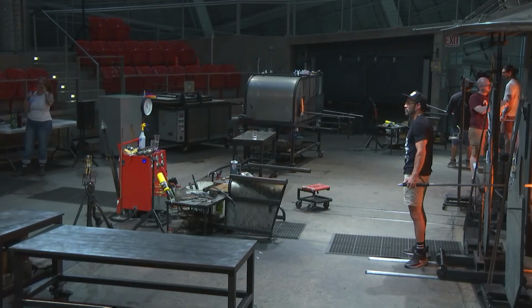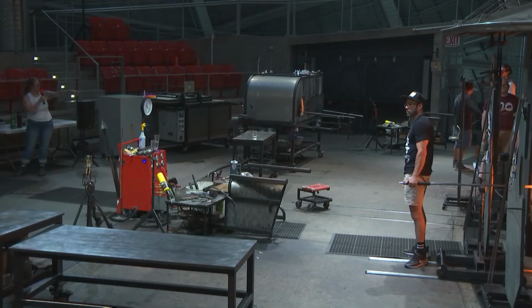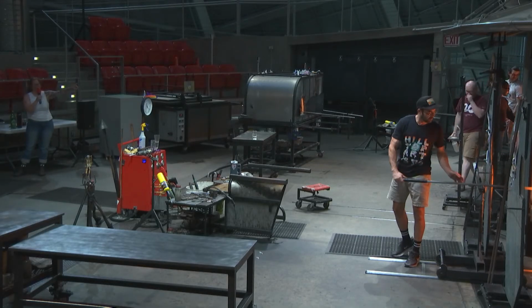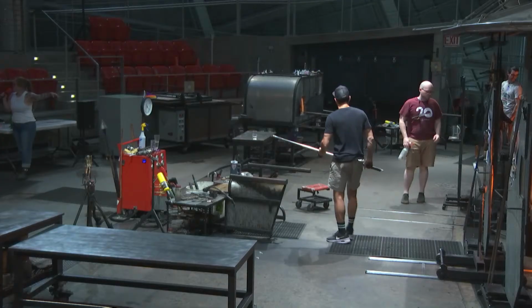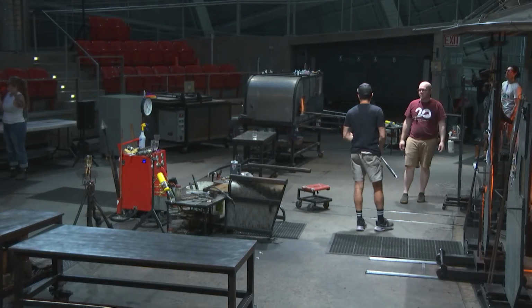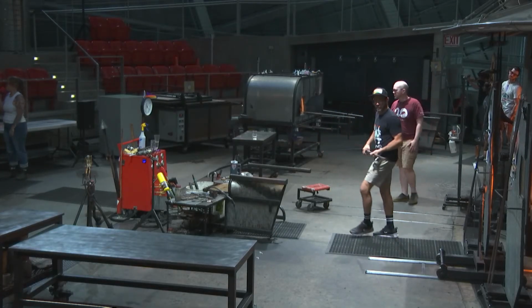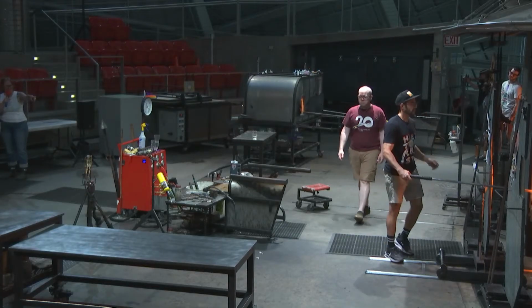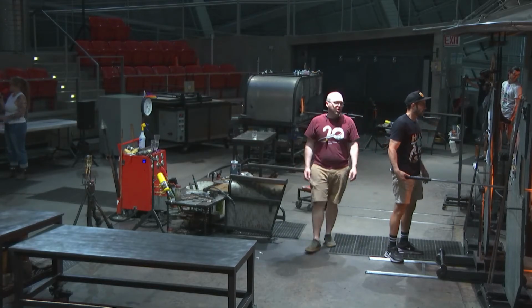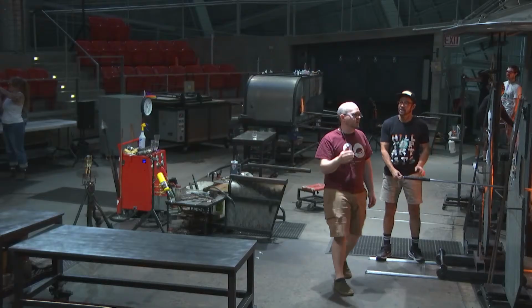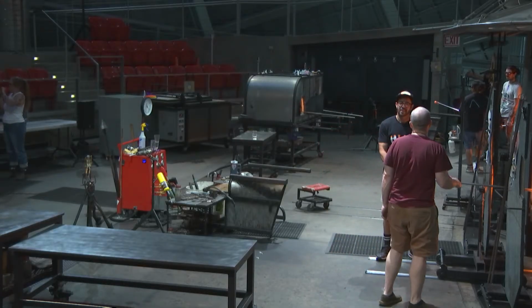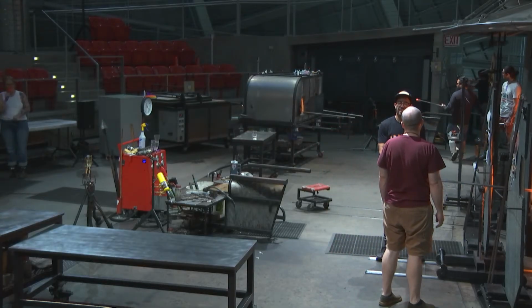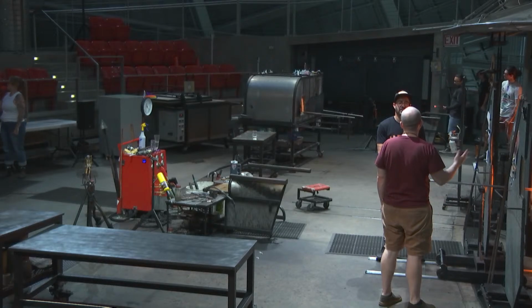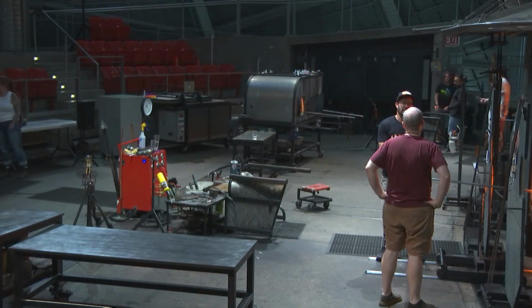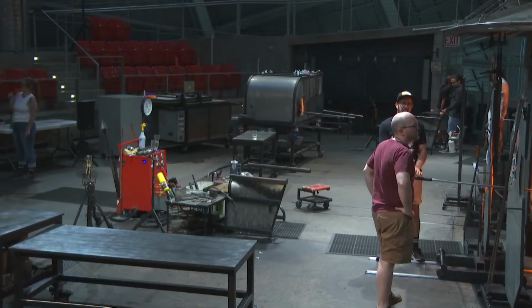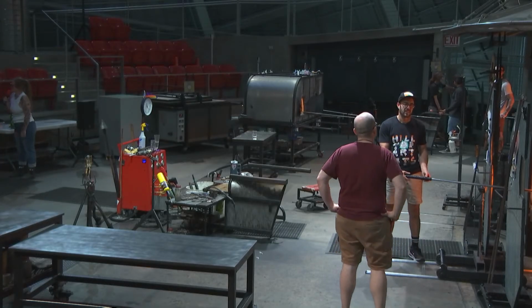It had too many bubbles in it. So Nick right now just sprayed water into the tank. The water pops the bubbles that are on the surface of that pool of molten glass inside. The reason they got rid of the bubble they had is because it had too many little bubbles from when you scoop the glass out. Sometimes you can trap a bunch of little air bubbles, and they just don't want those. So they're going to start over and do another one with one bubble instead of a bunch of little ones.